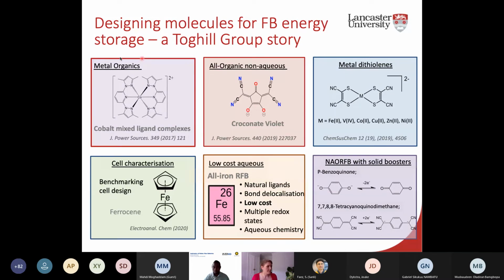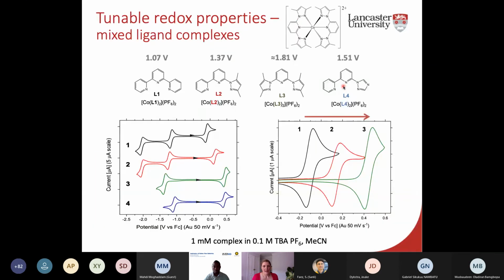And we've looked at metal organic complexes with mixed ligand systems. So we're manipulating the ligands. We've looked at organic, all organic metal free species in a non-aqueous solvent. And we've also looked at the impact of having a non-innocent ligand on our metal center. So one aspect was tunable redox properties. So can you improve your battery by having a solution where you can modify this ligand such that you then increase the potential difference between your redox species?